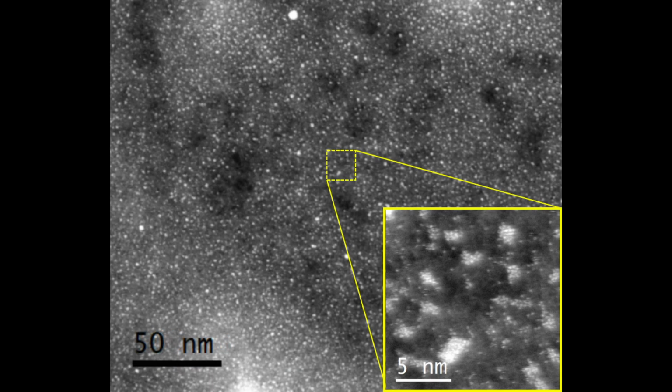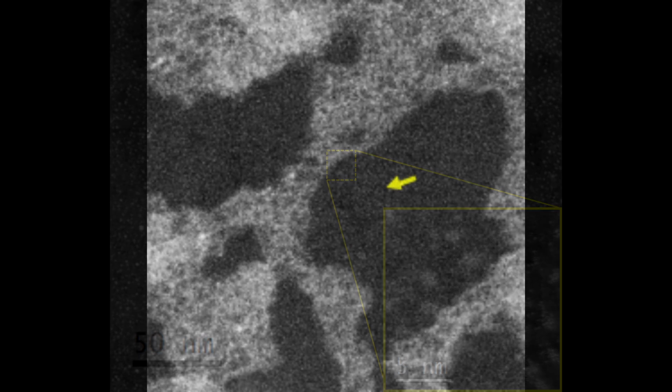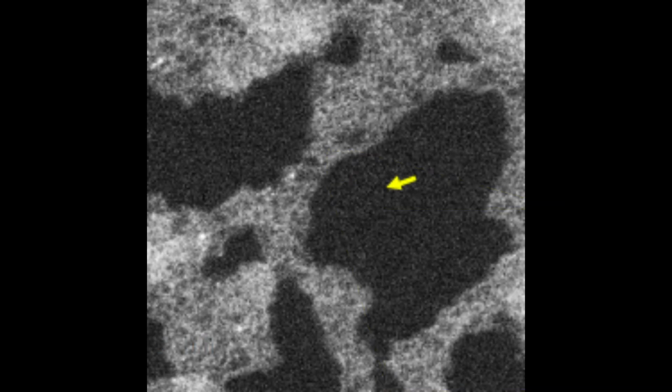If we zoom in to regions around the platinum lines, we can see that platinum atoms and small clusters are present across the graphene surface. In addition, most of the graphene in this region is well covered with additional contamination. As we move away from the deposition site, the concentration of platinum atoms decreases, but so does the level of the other contaminants. We were able to find regions where there were clean areas of graphene along with a few platinum atoms.